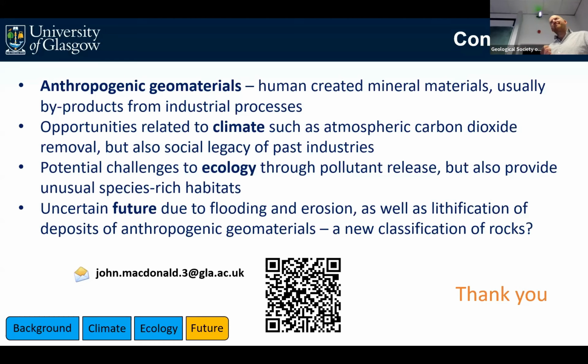If you were to go in and dig up these slag heaps, which are big mounds, so that the CO2 from the atmosphere could percolate and react with all of it, that would be good, but you probably expend a lot of CO2 digging it up. Equally, if you were to grind it down into a nice fine particle size, that'll make it really reactive, but slag is really hard. So it takes a lot of energy to grind it up, so you're probably going to emit quite a lot of CO2 doing that. So there's an interesting balance to be achieved in these things.